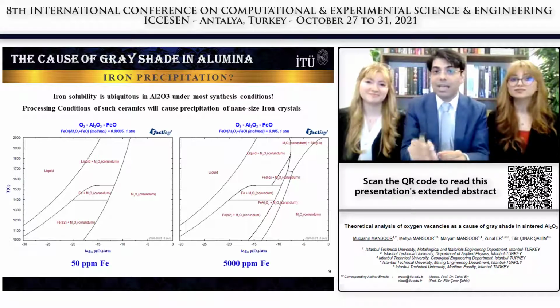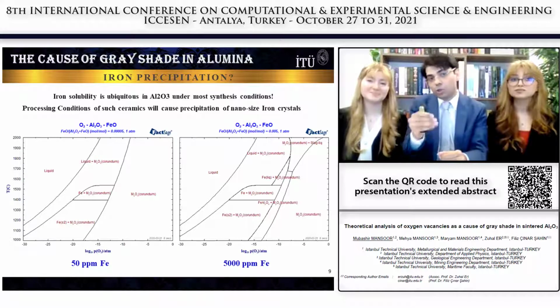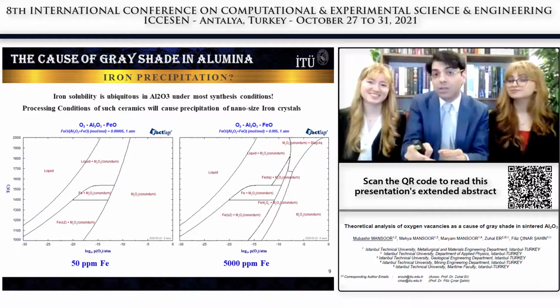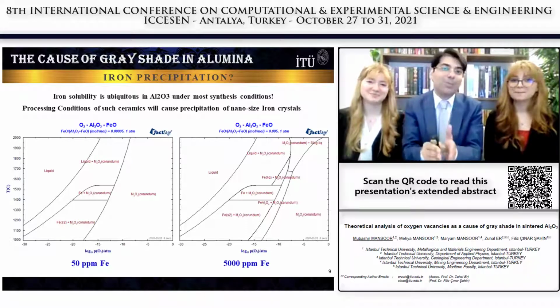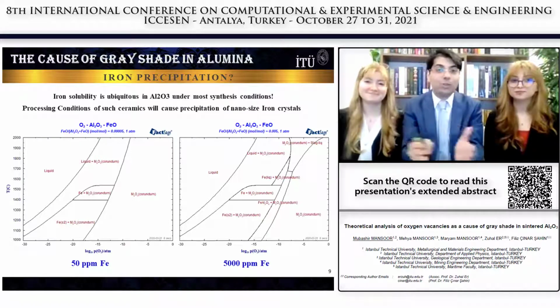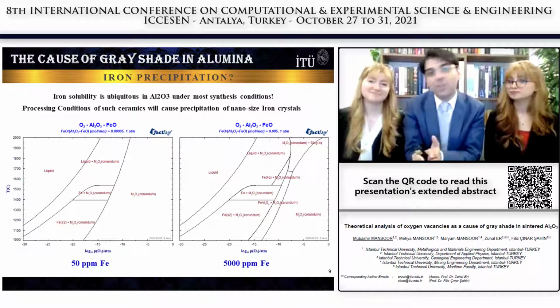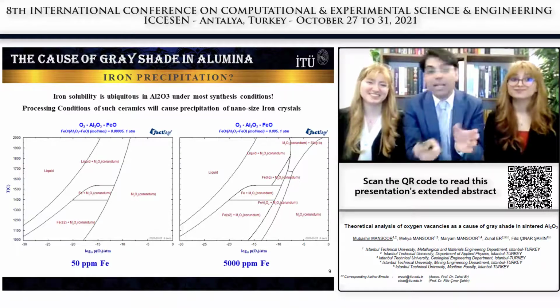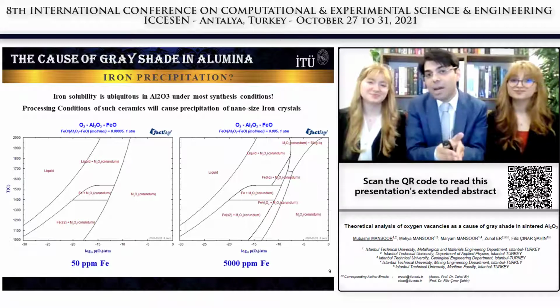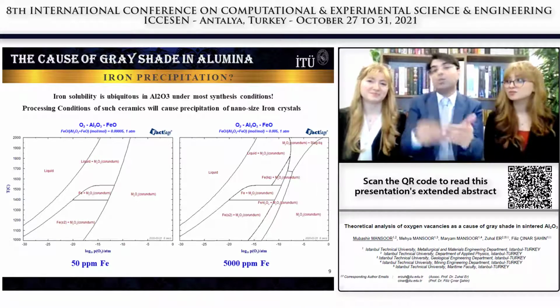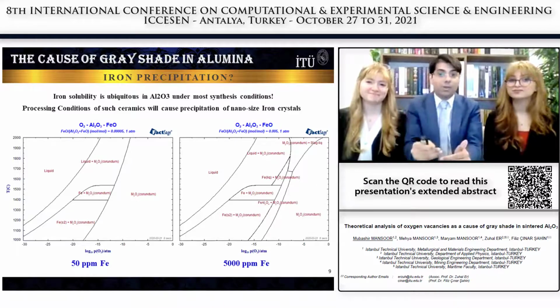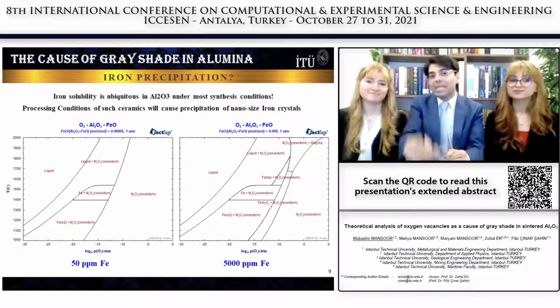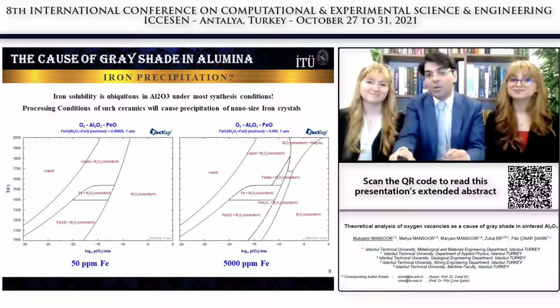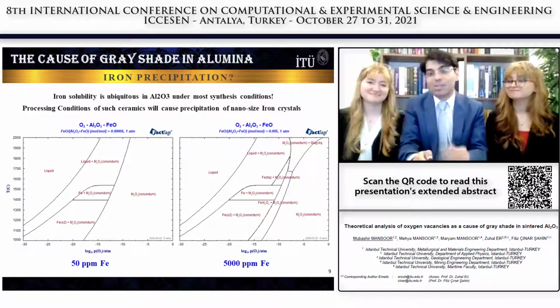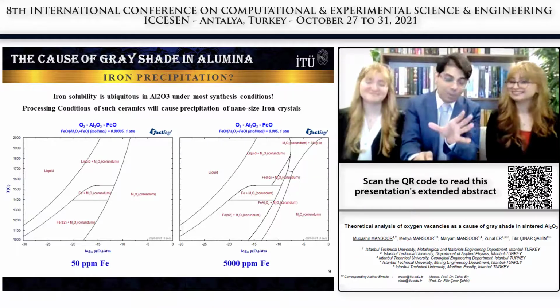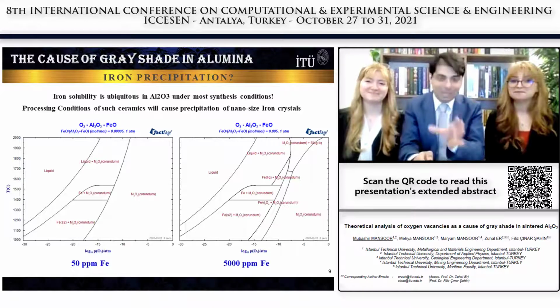So what happens is, as soon as oxygen partial pressure drops, precipitation of iron occurs. Now, even if there is only 10 parts per million available, when we consider the usual oxygen partial pressures during SPS sintering, this is inevitable. Now, this would also explain why these ceramics become colorless and fully transparent through subsequent heat treatments in oxygen-rich atmospheres, because then you would be actually redissolving that precipitated iron back into the alumina crystal. So this is a very good hunch to maybe start another journey or another hypothesis to go on to.